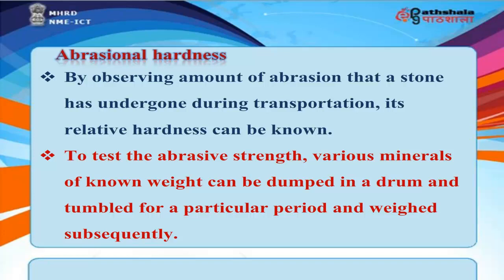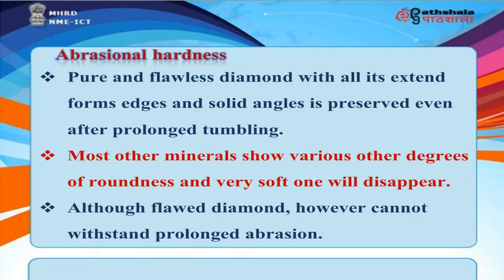Abrasional hardness. By observing the amount of abrasion that a stone has undergone during transportation, its relative hardness can be known. To test the abrasive strength, various minerals of known weight can be dumped in a drum and tumbled for a particular period and weighed subsequently. Pure and flawless diamond with all its extended forms, edges and solid angles is preserved even after prolonged tumbling. Most other minerals show various degrees of roundness and very soft ones will disappear. A flawed diamond, however, cannot withstand prolonged abrasion.